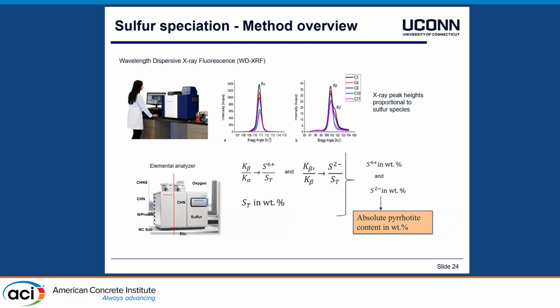Besides total sulfur measurement, we use the WD-XRF measurement to distinguish between sulfates and sulfide. If you use WD-XRF, you get different intensities, and those are at a specific angle for the sulfide or sulfate species. For example, the peak here, which we define as K alpha, and this peak here, K beta, and the satellite, K beta prime here, those are indicative of the presence of sulfates and sulfides. For example, the ratio between K beta and K alpha gives you a means of quantifying sulfates, sorry, and between the satellite K beta prime and K beta gives you a means of quantifying sulfides.